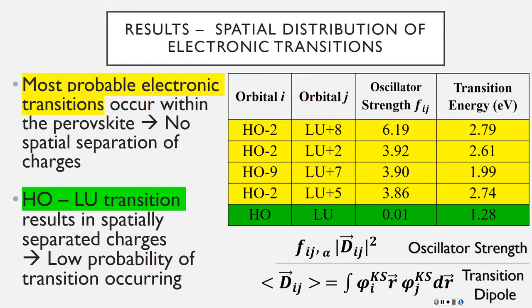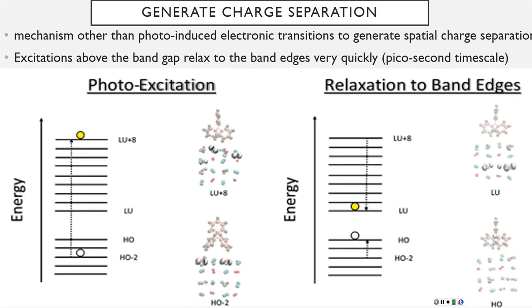So to summarize, the most probable photo-induced electronic transitions occur within the perovskite, and they don't produce charge separation, while the transitions that do result in spatially separated charges have a very low probability of occurring. So we have to consider a different method to get spatially separated charges.